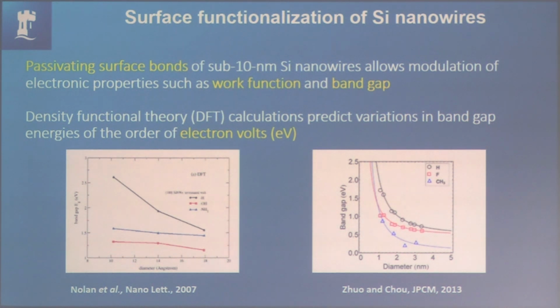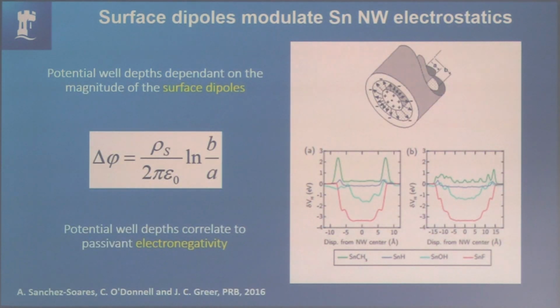And I don't know if anybody's actually measured that in detail. I know that people have measured the band gap widening with different terminations, but I don't know if there's ever been a side-by-side comparison on the same system. We were looking at alpha tin because in very thin layers you can stabilize it. It's not stable in the bulk. There's famous historical stories about buttons that once they froze, they became alpha tin and fell off.